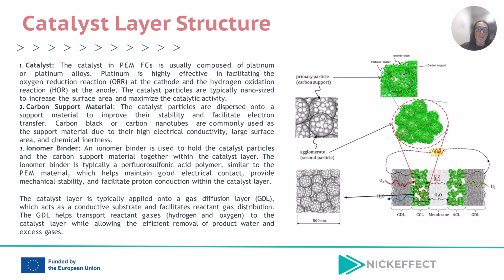The catalyst layer is incredibly thin, usually between 5 and 30 microns. Despite its size, it has a complex internal structure with multiple phases, porosity, and active reaction zones. When we look at it under a scanning electron microscope, we see an agglomerate-type structure. The electrocatalyst is supported on carbon agglomerates, and it's covered by a thin layer of ionomer that helps manage proton transport.